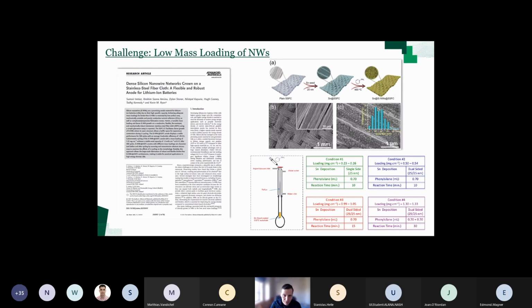So by varying how much tin you deposited on, whether you deposited on single side or both sides of the cloth, and by varying reaction time, we were able to vary the mass loadings to between about a quarter of a milligram per centimeter squared up to 1.3. So we couldn't reach the 1.6, which we tried to reach, but this was the max we could get. So we had 4 different data points at least.